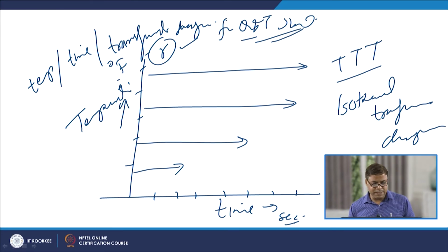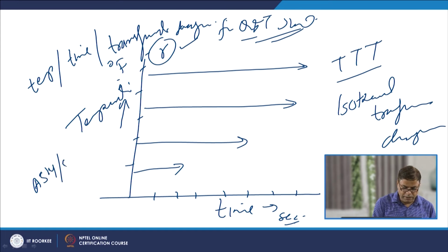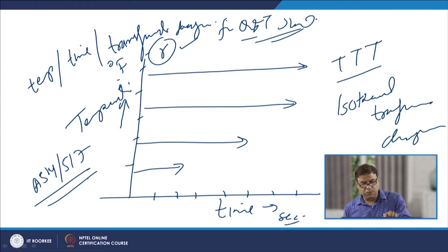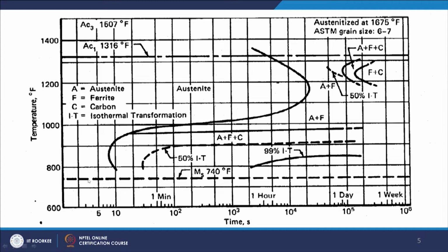So, for Q&T steel, which is most common, like the A514 and 517 category, we will be looking into the isothermal transformation diagram. If we see, there are 2 or 3 zones about which we can say what happens to the steel when it is exposed at a constant temperature in the range of 1100 degree Fahrenheit to 1300 degree Fahrenheit. This is one zone. Then another zone is 950 to 1100 Fahrenheit. And then what happens when steel is exposed at a temperature below 950 degree.